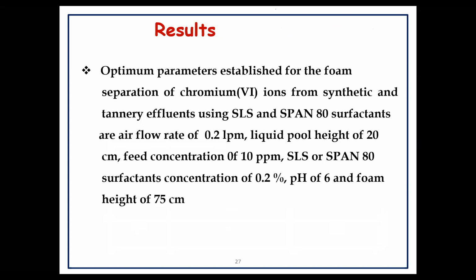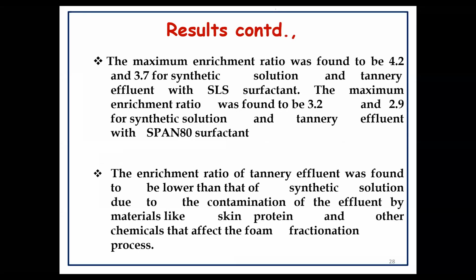Since the actual effluent has a very low pH, it has to be adjusted to 6, and the foam height was around 75 centimeters. So these are the results we got. We got all these optimization results using statistical optimization methods. And once we optimized all these parameters, we applied it for the continuous column studies also. Initially, we did experiments in a batch column and extended to continuous column operations.